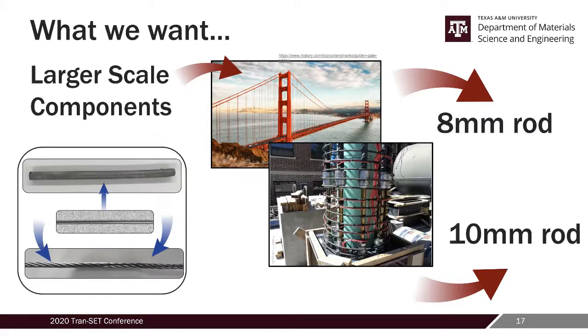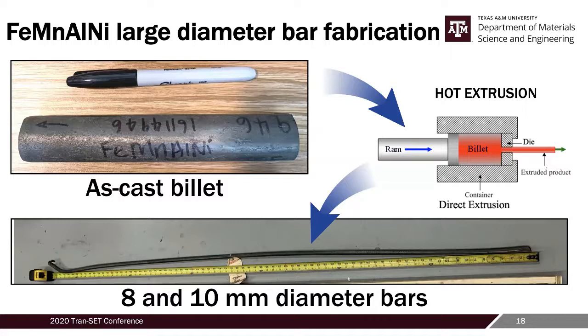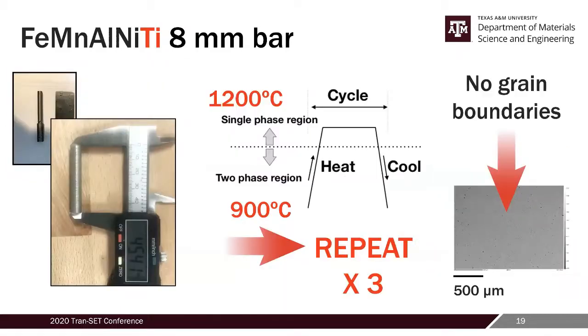But in the future, what we want, of course, is much larger diameter bars, 8 millimeter to 10 millimeter rods. So in iron manganese aluminum nickel and iron manganese aluminum nickel titanium, we fabricated these bars. What you do is take this as-cast billet and hot extrude it at 900 degrees C. When you do that, you can get 8 to 10 millimeter bars. And after that, you need to apply those heat treatments again, which are very critical.